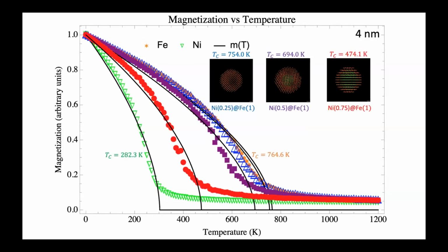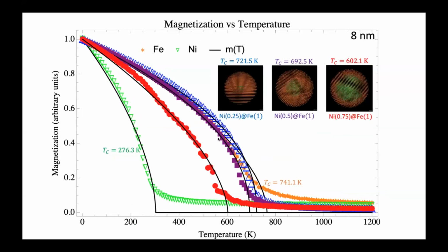Now, when you look at the core-shell nanostructures of these magnetic nanoparticles, first we look at the 4 nanometer particle, and we play with the ratio of the nanoparticles. We have pure iron, and inside, as a core, we use nickel. When we increase the ratio of the core, we see that the Curie temperature decreases as it tries to get back to the original Curie temperature of nickel. And when you also increase the size of the nanoparticle, making it 8, we also see the same trend.